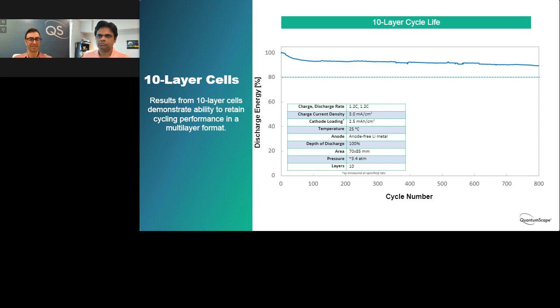So this cathode loading is a bit lower than what we had shown on previous cells. And I think one of the main reasons for that is that we measured this cathode loading at what turned out to be a 1.2C rate, so at a slightly higher rate. It just happened that for these cells, we were doing faster capacity check cycling than we had done previously. So that's one reason to see slightly lower cathode loading, but it's not something at all systematic. We wouldn't expect that as we further increase layer count, the cathode loading would decrease. Actually, we intend to increase cathode loading above 3 milliamp hours per square centimeter going forward.